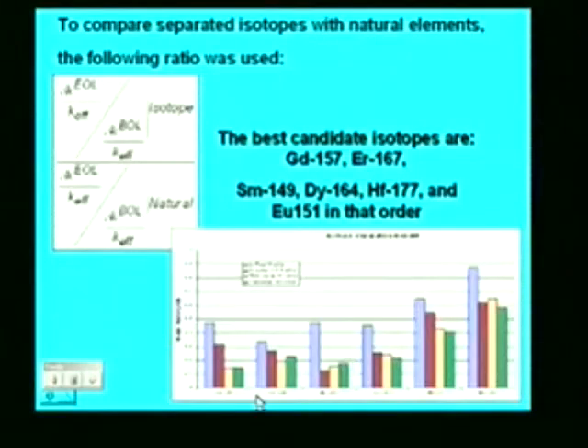And if we look at some of these isotopes, gadolinium-157, samarium-149, notice in this region they're all below 0.5, and depending upon the configuration, we can get them well below 0.2. So it looks like we can do a lot of good by separating isotopes, and we find the best candidates are gadolinium-157, erbium-167, samarium-149, and dysprosium and hafnium isotopes in that order.